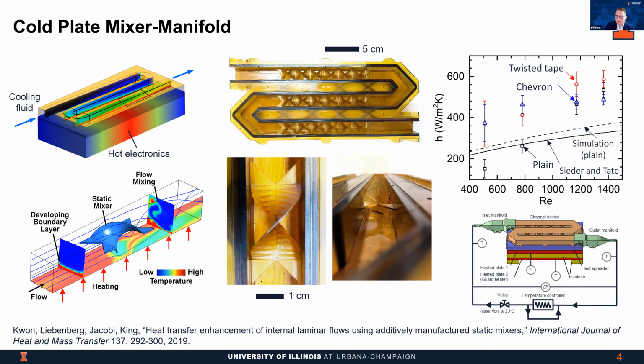I want to point out something that helped to motivate this particular work: the availability of new additive polymers that have very high accuracy and resolution in printing. This particular material is called cyanate ester, which has only been commercially available for the last couple of years. It's available from a company called Carbon 3D. And it actually has the highest temperature stability of any additive polymer, over 200 degrees C. It's also extremely strong. And so you can see here that we fabricated the tape and the channel all as one monolithic part. So this was a single print to make this manifold part.